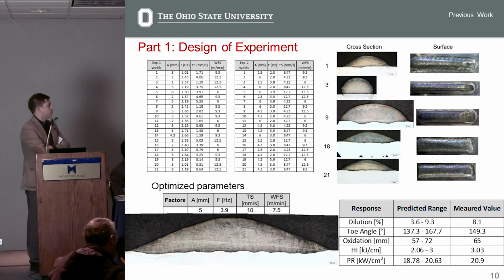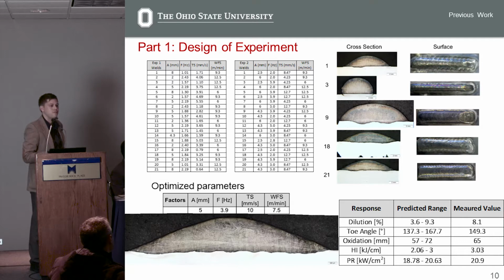Part one of the work entailed a design of experiment to optimize CMT welding parameters. We did a minimum design of experiment. We did two of them, which kind of defeats the purpose of a minimum, of 21 welds each. We tracked the variables of dilution, toe angle, oxidation, which was sort of a derived property, heat input, and power ratio. At the end, the factors of the CMT welding, the weave amplitude, the weave frequency, the travel speed, and the wire feed speed were optimized with 5 millimeters, 3.9 hertz, 10 millimeters per second, and 7.5 meters per minute. And the actual versus predicted measurements fell well within, or close enough to the range that we accepted it as optimized weld parameters.